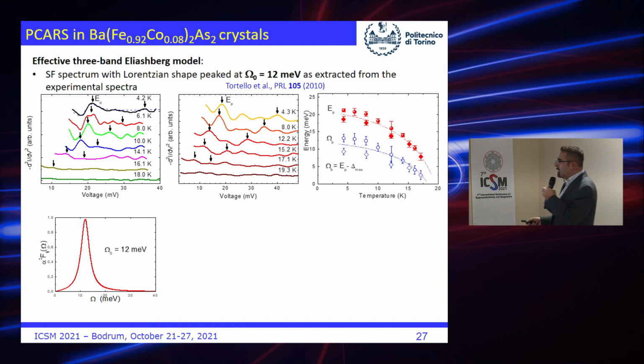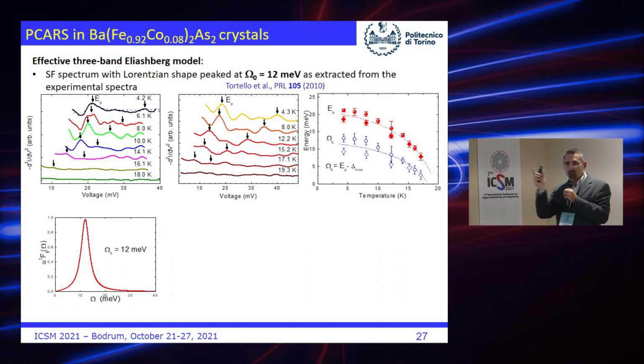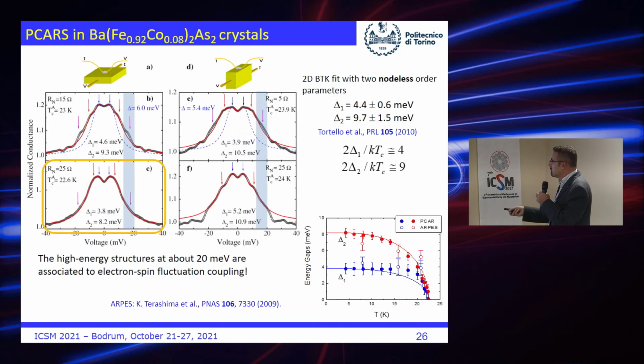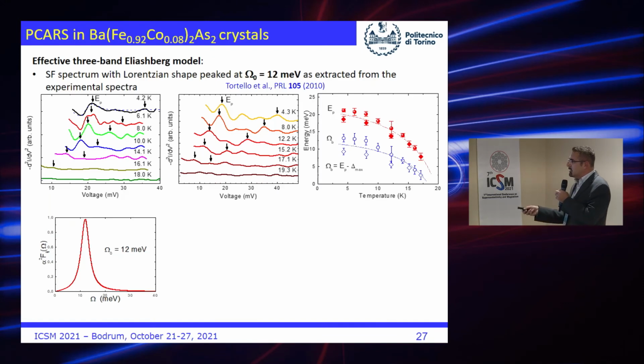of points. But now we know from what I've seen in the sample that the peak occurs at omega 0 plus the maximum delta, and the maximum delta is of the order of 10 here. Now we can subtract the gap. So from these points we subtract the gap obtained in this curve. That means it was about 8. So from here we go here. In this case, we subtract the gap that was of the order of 10, so from here we go here,